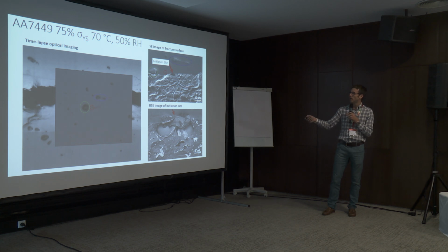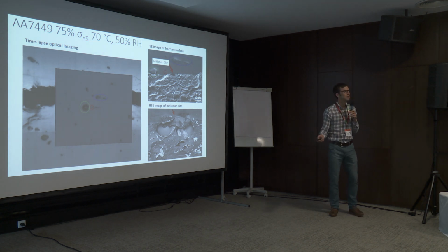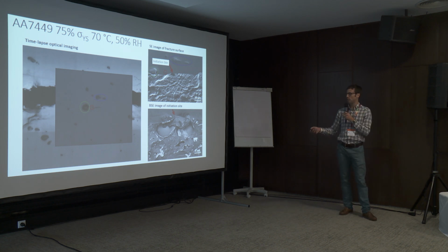But because we've got these in situ images, we can tell that the crack starts at exactly this point. And we can find that on the fracture surface in the SEM and see that it's a small gas pore cluster associated with an Mg2Si particle in this 7449 sample. And it's quite surprising because this is such a small feature. Each of these pores is less than 10 microns in size, and so is the particle, and it's not the biggest feature in the local neighborhood.